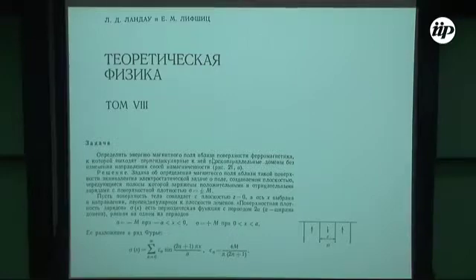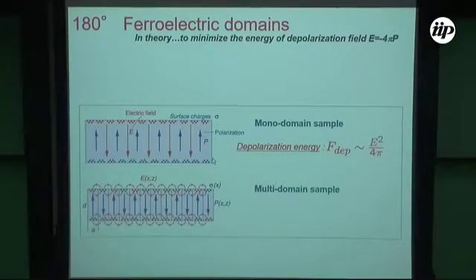And actually, the answer to this, I think everybody who passed the Landau minimum knows this problem very, very well. This was published in '37, and after that Landau and Lifshitz posed this famous problem in the theoretical physics book volume number 8, that because of the depolarization effects, the magnet, but for ferroelectrics it is even much more actual, will split into domains. Indeed, when we have a monodomain sample, we have this very, very bad depolarization field that will kill ferroelectricity.